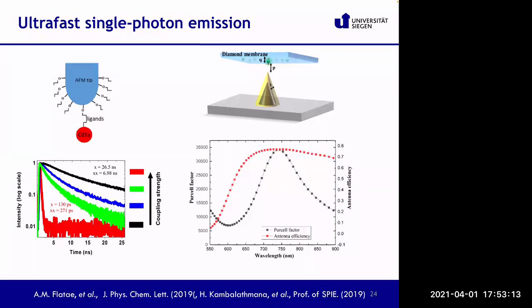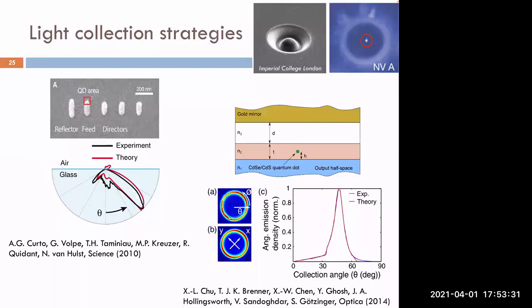And so here we also have some calculation which show enhancement of 4 orders of magnitudes. And currently we are trying to do the experiment. So this will be a concrete way to make emission extremely fast and therefore the source extremely bright. And another problem is about the collection. So these color centers are, first of all, dipoles. So you know that it's not easy to collect the light from a dipole.